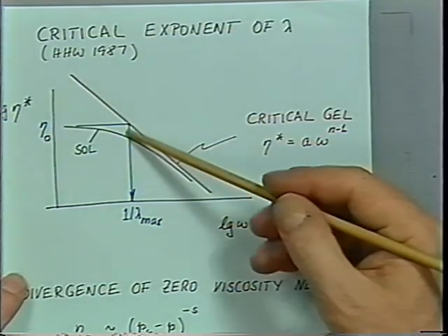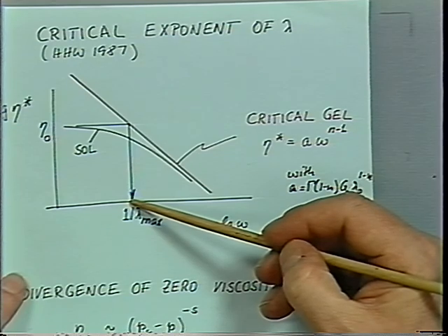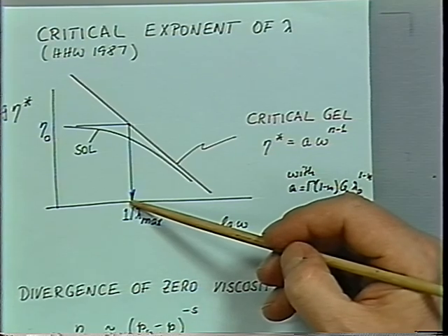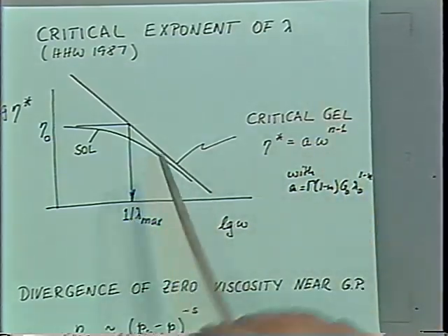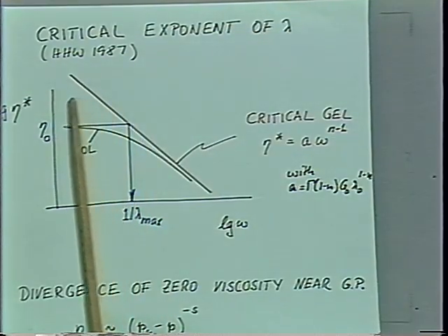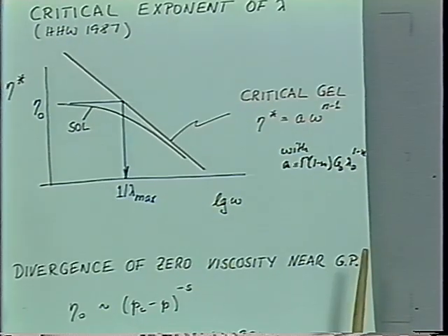And this curve now is intersected with the value of the viscosity and gives us an intersect frequency. And 1 over that frequency will be defined as the longest relaxation time. That's our choice, or that was my choice. There was no definition for that, so I've just defined the longest relaxation time as 1 over this intersecting frequency. And as the viscosity increases, the intersect moves to lower and lower frequencies, and that's the typical behavior. The relaxation time assumes larger and larger values.